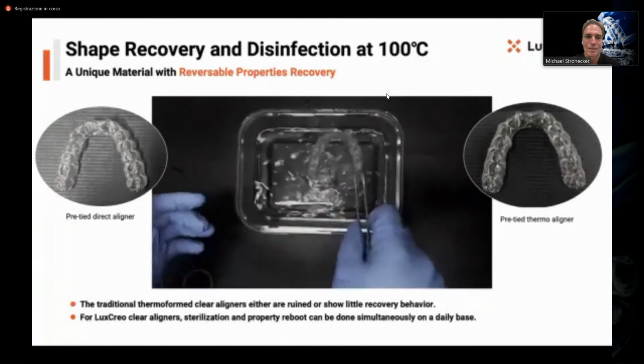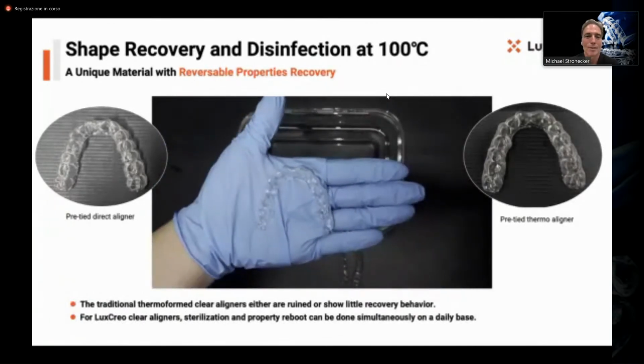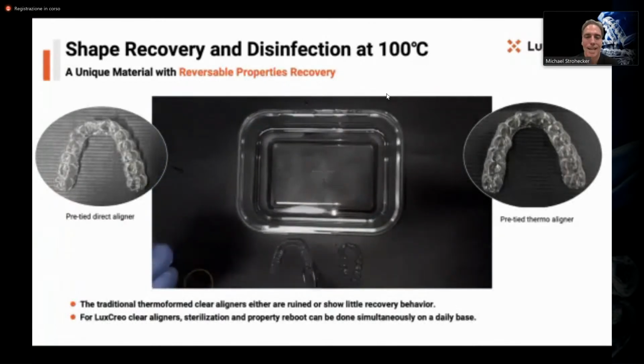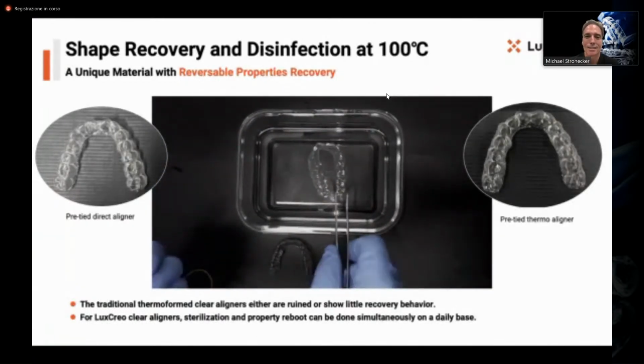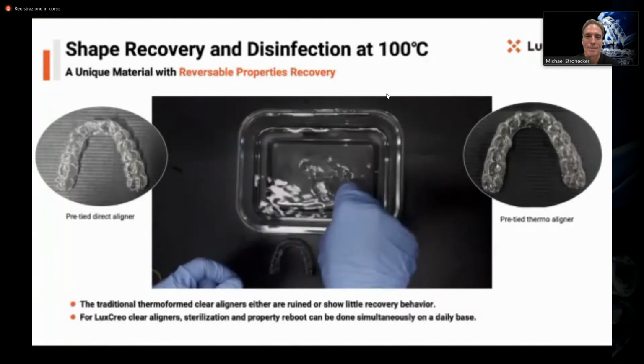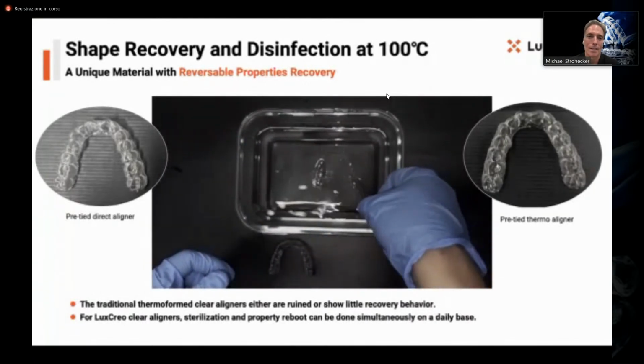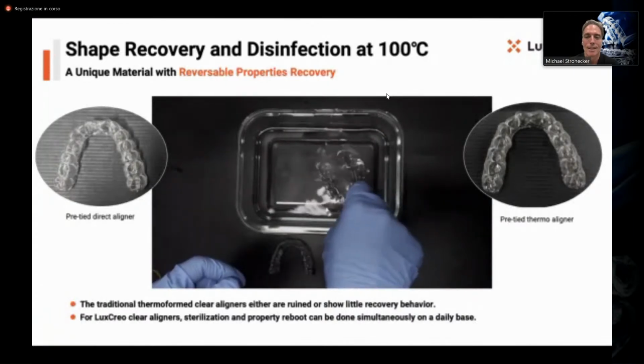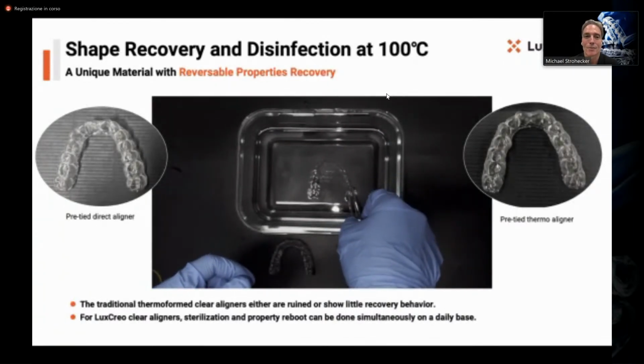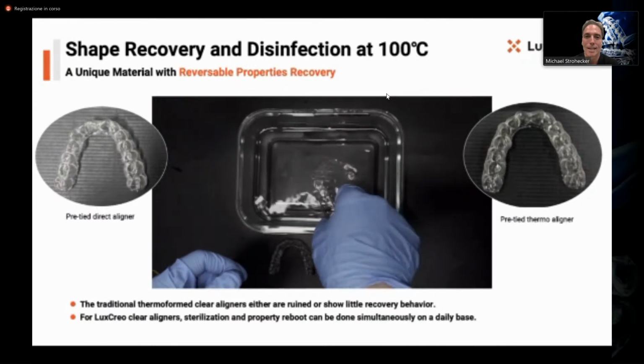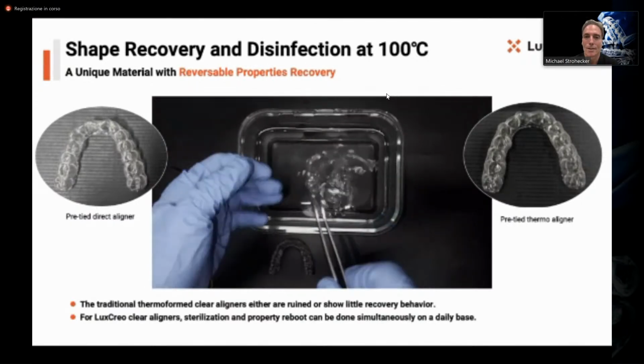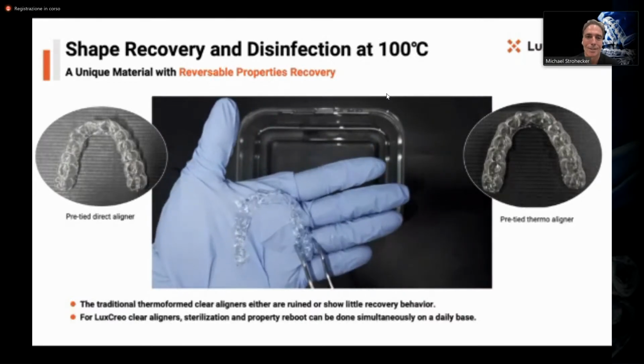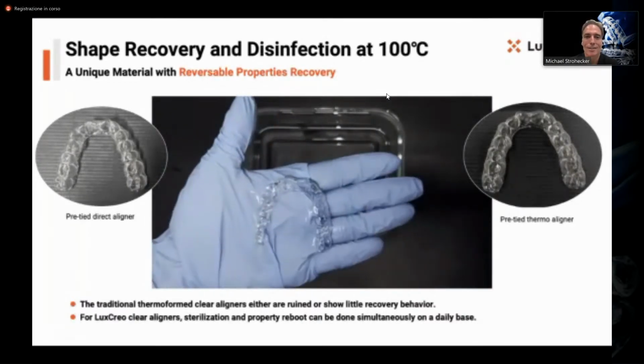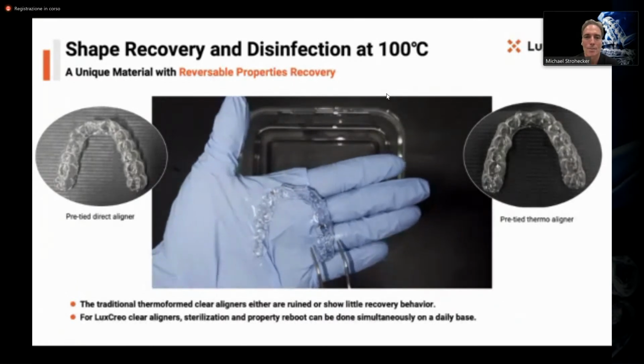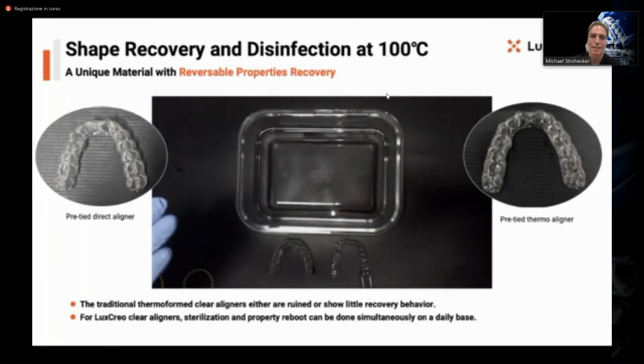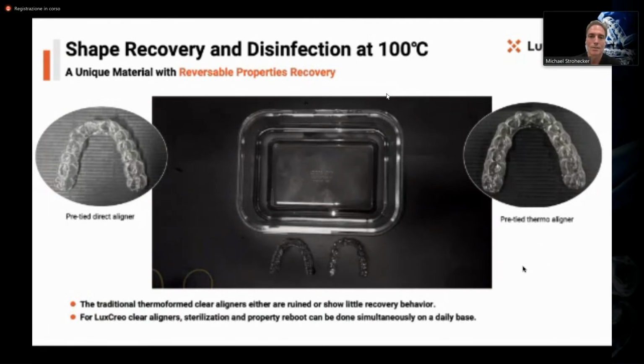And you look at the result. It's perfectly back to shape. We've done this many, many times, and scanning data proves that we get around 99 to 99.8% accuracy. Now you put the thermoform in, and we know that because it's a thermoplastic, this is just not fair. The thermoform is not able to do this. That's why you have to use chemicals, or a toothbrush and toothpaste, which also affects the clarity. Now it may look like it's shaped, but it's never going back on your mouth. The molars are compressed. It would never fit again. So that's why I say don't drink with a thermoform in your mouth.